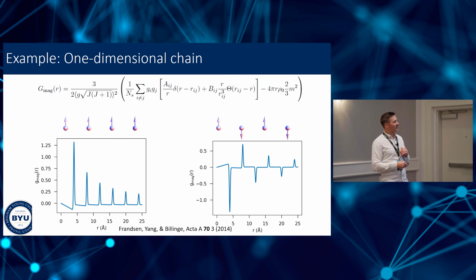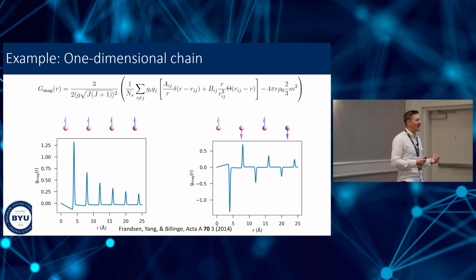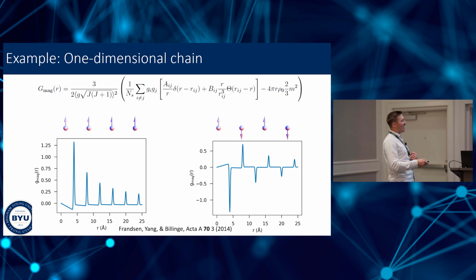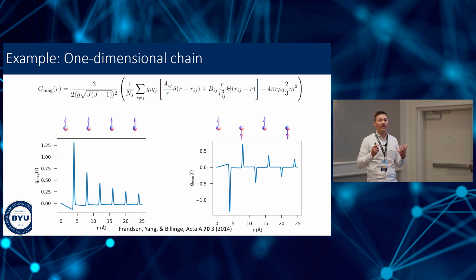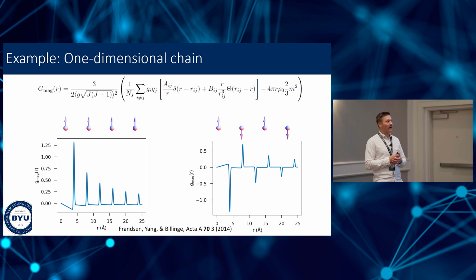The magnetic PDF is just a series of positive peaks, all right? And the first peak here occurs at the nearest neighbor distance, the second peak at the second nearest neighbor distance, and so on and so forth. And there are positive peaks because the spins are aligned with each other. If you have an antiferromagnetic chain, where we have alternating spin directions, then we have alternating negative and positive peaks in our magnetic PDF. So it's a really nice intuitive function. You can look at a glance and know what the local magnetic correlations are in your material.